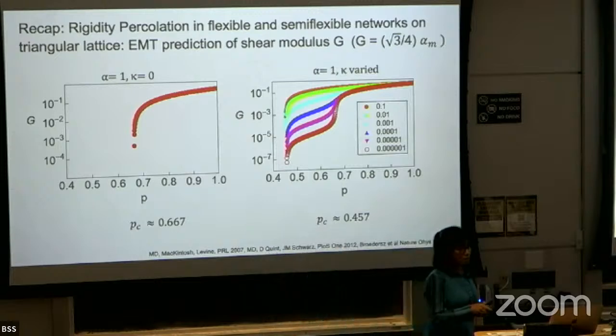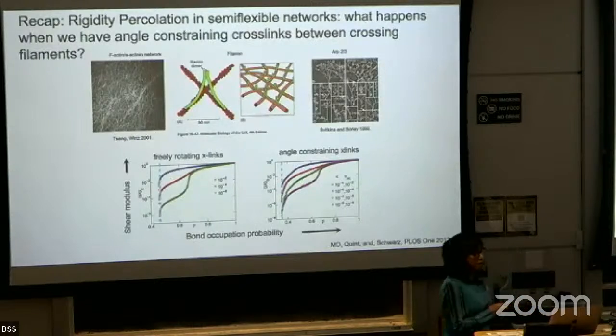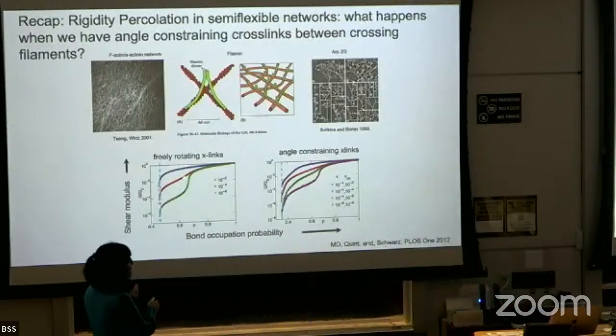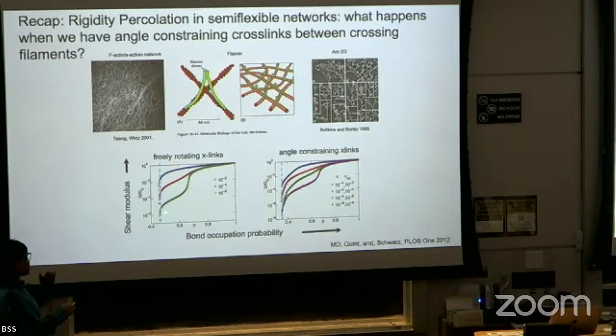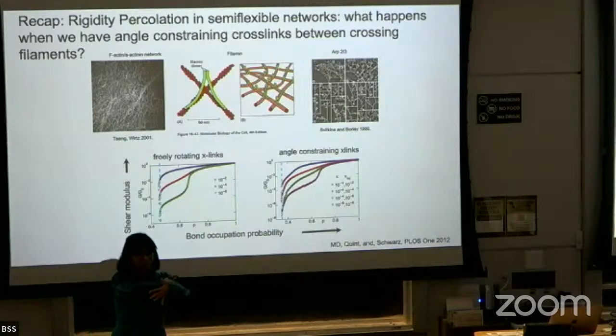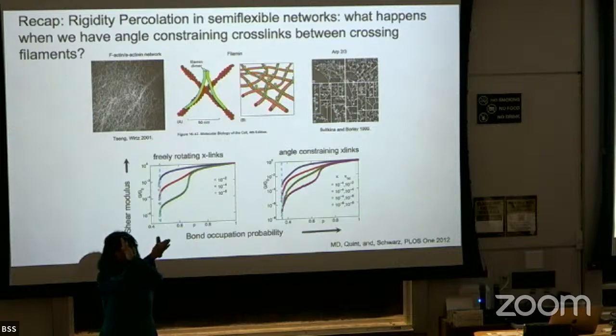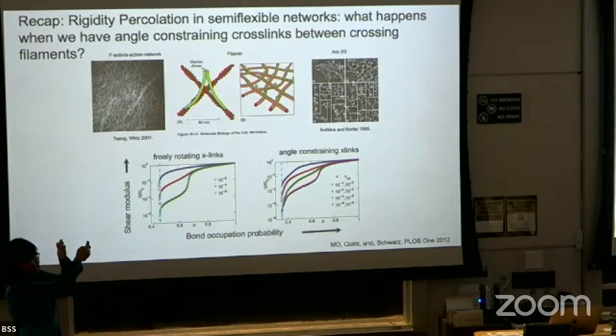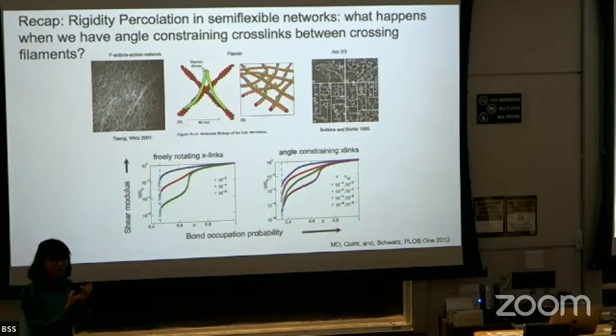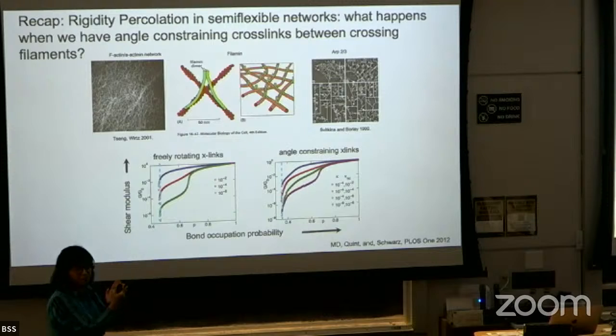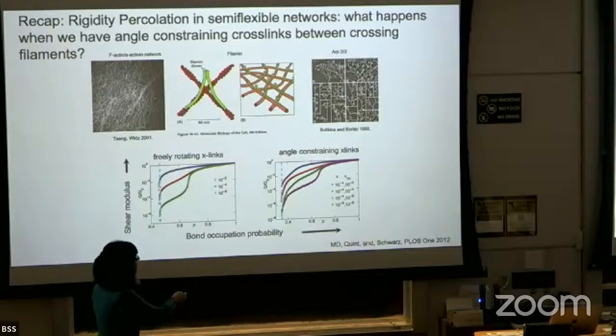Other questions? Okay, and then still doing recap. We said that if we added these bending energy, our percolation threshold moved from 0.67 to about 0.45, 0.46. On top of that, if we added other constraints that will constrain the angle between crossing fibers, like Leo was suggesting the other day, and you can see this in networks of actin cross-linked with filamin or actin branches growing with Arp2/3. There you will have this additional angle constraining crosslinks. And if you did the effective medium theory or minimized the energy, then what you will see is that the percolation threshold moves even further to the left, and it's like 0.36 now.